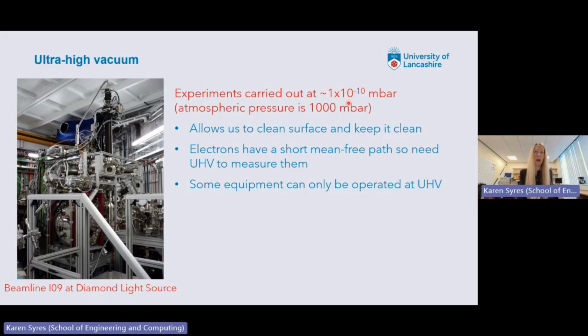The reason we do that is because if you have a surface and you just hold it in air, it's going to get contaminated really quickly just by things sticking to it, on the order of nanoseconds. By putting it into a vacuum, there are processes we can do within the vacuum to get that surface atomically clean. So there's literally nothing on the surface, and it will then stay clean. Then we can deposit things that we're interested in onto the surface to understand the physics between these different materials.